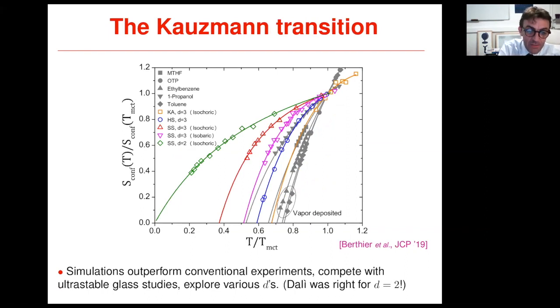So what about the work of Kauzmann itself? Can we revisit it and say something? So similarly to Kauzmann, we can collect the new data obtained from the physical vapor deposited glasses and the new computer simulations to look at the behavior of this configurational entropy in various supercooled liquids. So the gray symbols here are the old literature data, the ones that Kauzmann had used 70 years ago, made more precise by newer experiments, but essentially the data look the same. So there are novel data in this. So first of all, you can see these circles here. These circles have been estimated using the vapor deposited glasses I mentioned before. And as you can see, these data go much, much closer to the Kauzmann temperature as compared to the 70 years old data of Kauzmann.